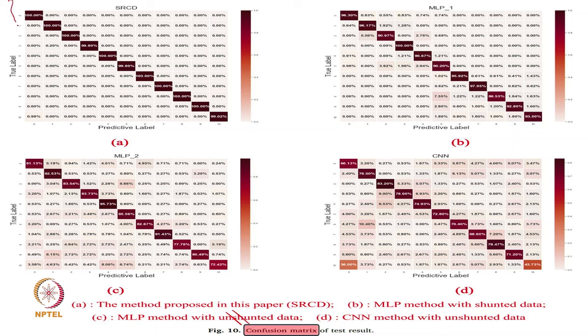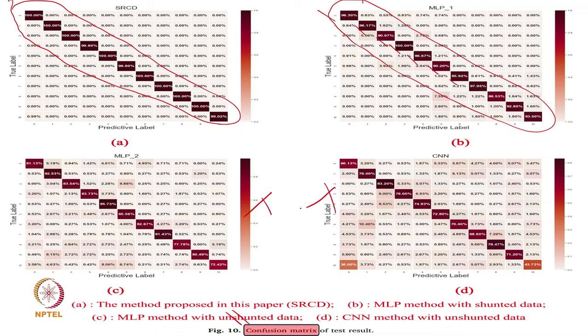You can see in the confusion matrix, they are mostly getting 100%, 100%, which is again hypothetical. We may not get 100%. It may be 90%, 95%, maybe 97%. With MLP1, when they are using two algorithms, they are also getting reasonably good results: 96.3%, 96.17%, 90%, 100%, 96.67%. So they are getting reasonably good results, while these other results are generally bad.